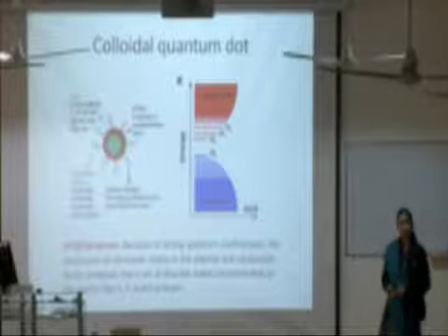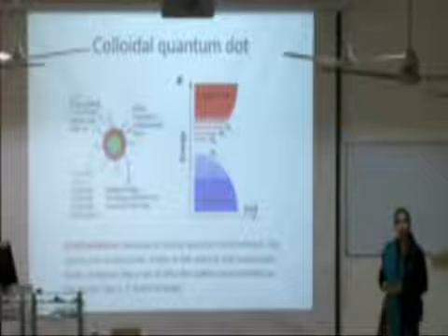So now if you look at the energy versus the density of states for a single colloidal quantum dot, because of strong quantum confinement, the continuum of states now gets reduced to a set of discrete energy levels, and these discrete energy levels in the valence and conduction band resemble the atomic s, p, and d orbitals of an atom, so hence the name artificial atoms.